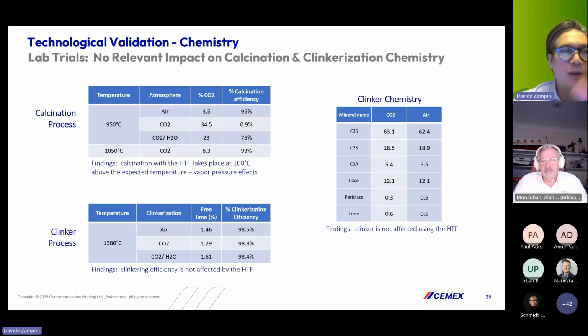Well, because the CO2 is in the gas, we have a vapor phase effect. So we do increase slightly the temperature of calcination, but that's not a big deal. We look at the clinker chemistry, and basically, we're very satisfied, and we have a perfect match with what we would normally produce in a regular cement plant that's burning other types of fuels.